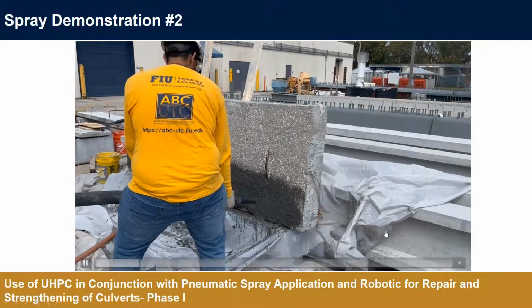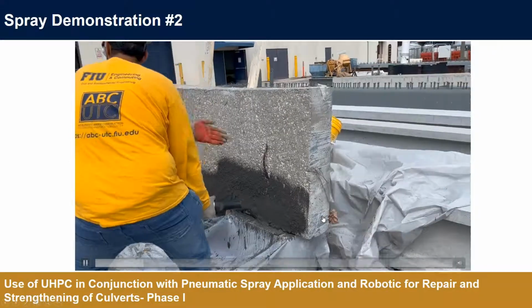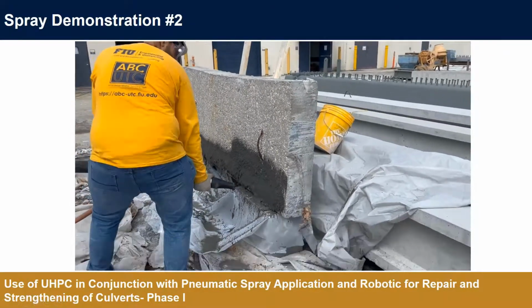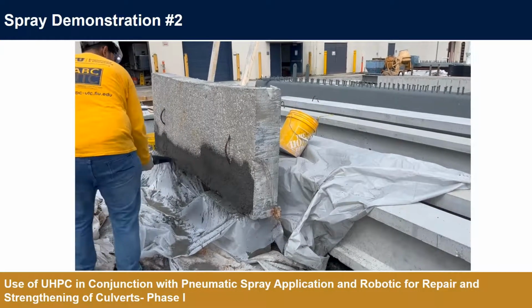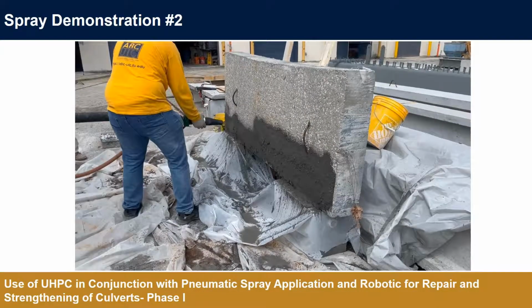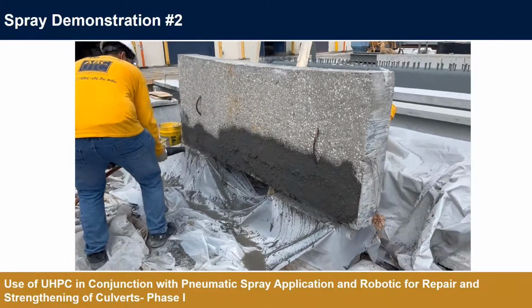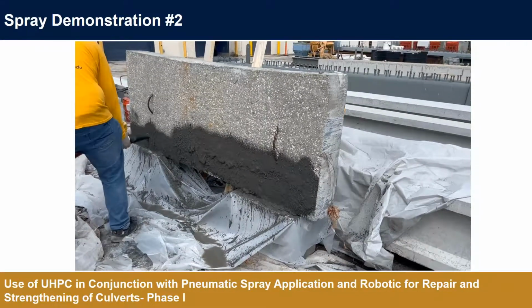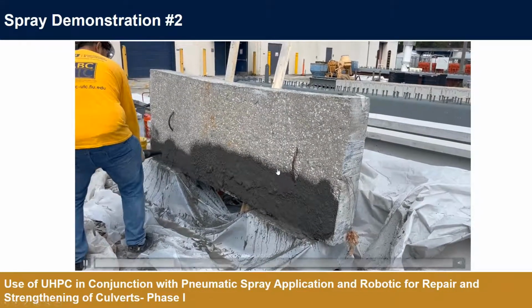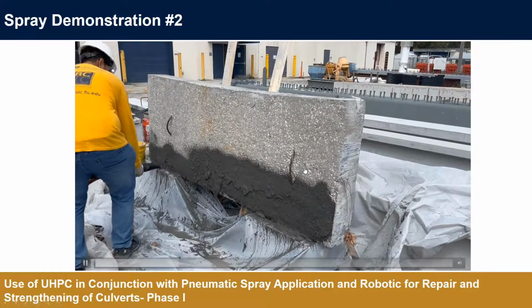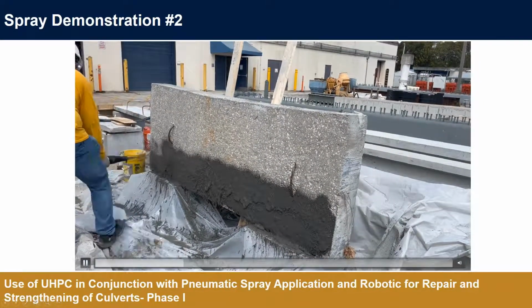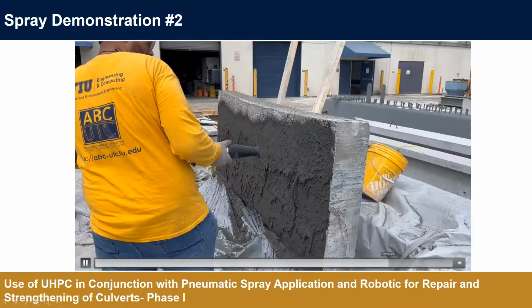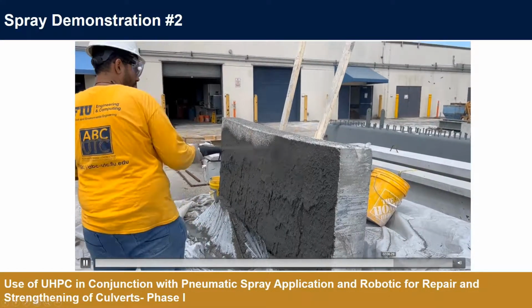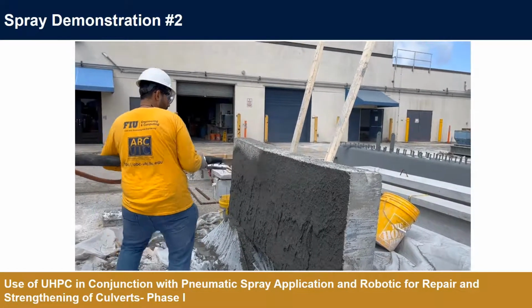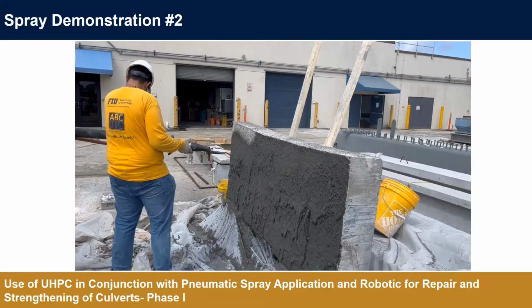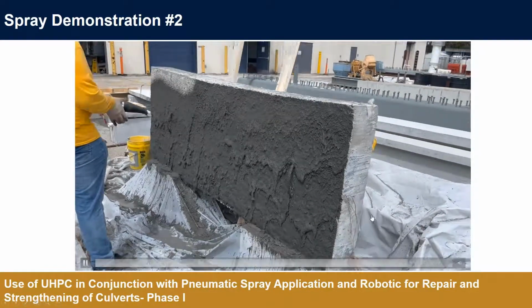There is a lot of detail that we will follow up in some publications in the future, but we were using an ABC UTC mix where we reduced the water to cement ratio in order to reduce the flowability. And if I just move to the end, we were able to complete like 3 complete passes of shooting of the UHPC for the specimen.